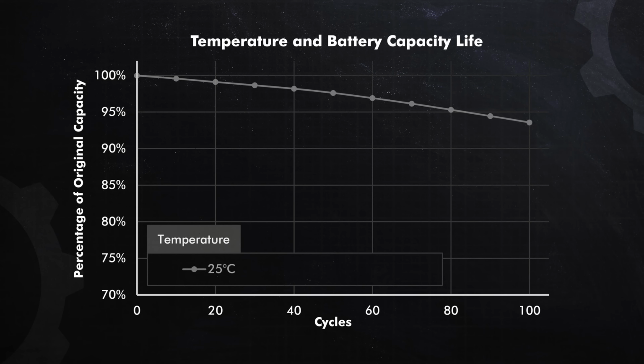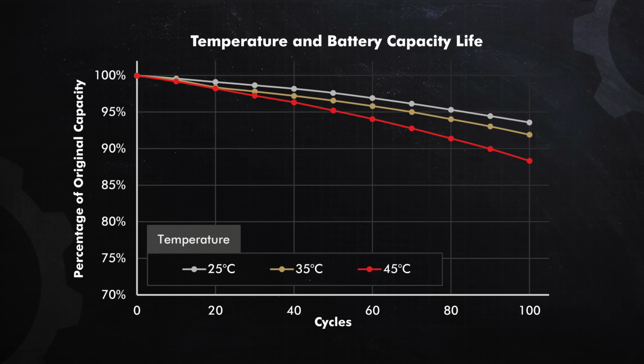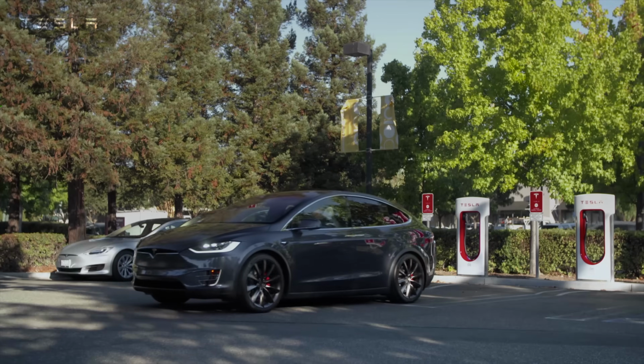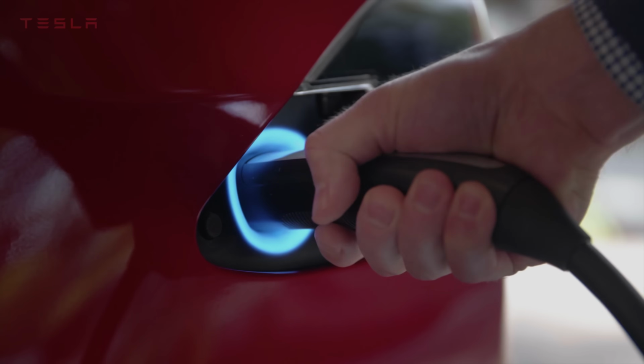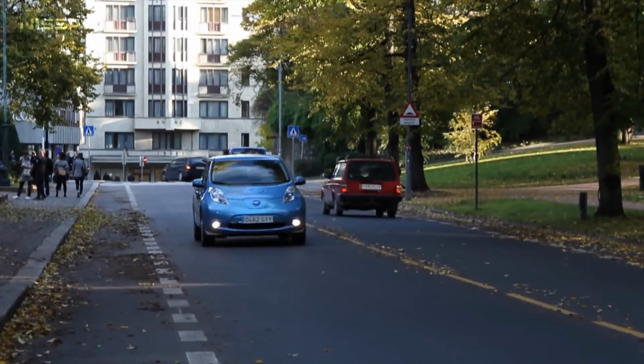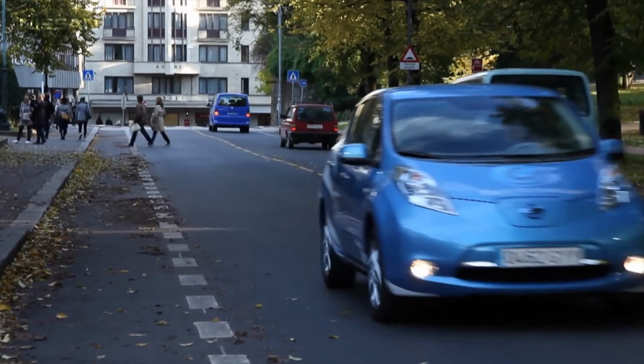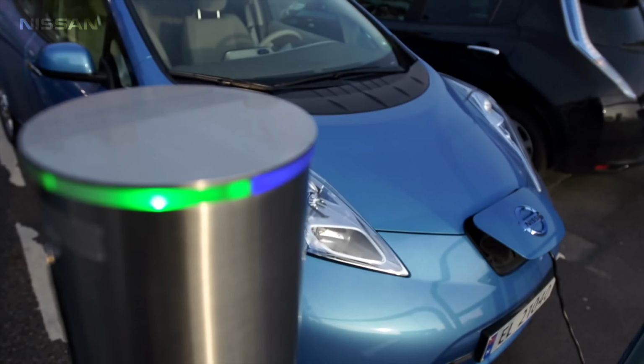The relationship between high temperatures and capacity loss is well documented. In these findings here, you can see that at 25 degrees Celsius, the cells lost around 7% of their original capacity after 100 cycles. However, when the operating temperature was increased to 45 Celsius, over 12% of the original capacity was lost over the same number of cycles. As we know, the battery degradation is directly linked to the number of charge and discharge cycles, but it's less well known that a partial cycle does not count the same as a full cycle.